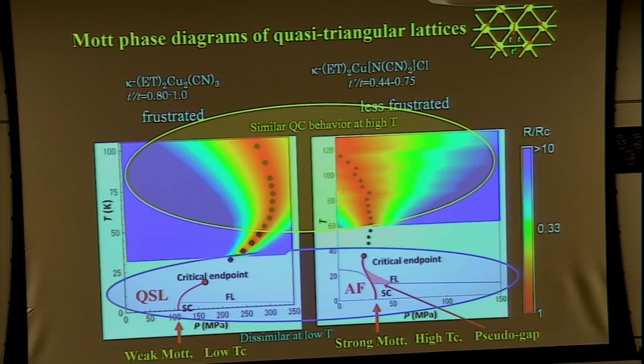Yeah, we determined that with T minus TC, in this temperature range, the resistivity is scaling. At high temperatures, the critical TC is in this case 20 or 15 Kelvin. So the data is also scaled if we use T minus TC instead of T. But in the low temperature region, the scaling fails. Rather than T minus TC, T scales the data. That is our feeling, but we cannot say definitively whether T minus TC scaling is ruled out or not. It is not definitively answered.